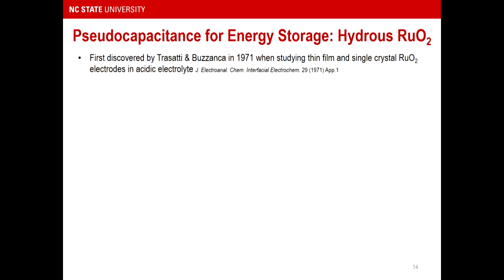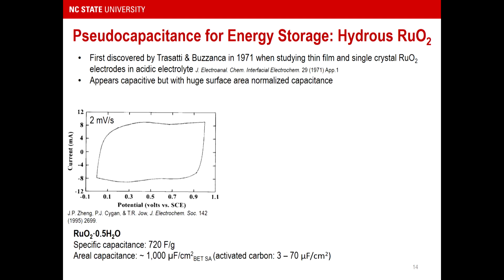It wasn't really until about a decade later that this concept was considered potentially useful for energy storage, and that was with the discovery of the very, very capacitive response of thin film ruthenium oxide. And it looks something like this. This is hydrous ruthenium oxide, cyclic voltammogram at 2 millivolts per second, a specific capacitance of 720 farads per gram. So several times larger than what you can achieve with activated carbons. Based on the BET measured surface area, that would correspond to an areal capacitance of about 1,000 microfarads per square centimeter. So tremendously bigger than what has been measured at activated carbons.